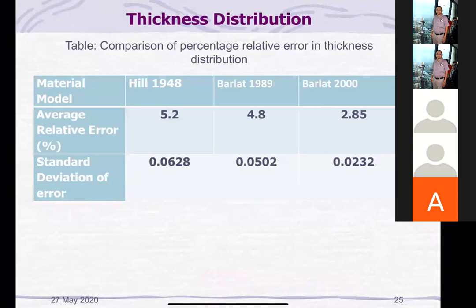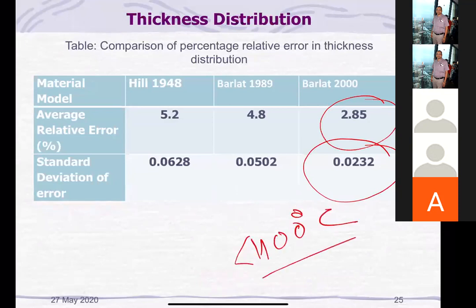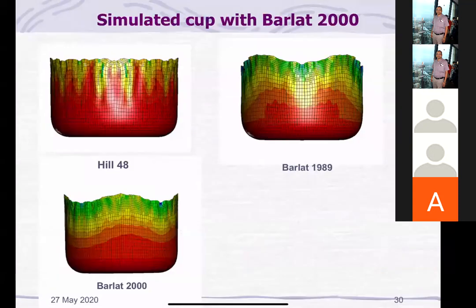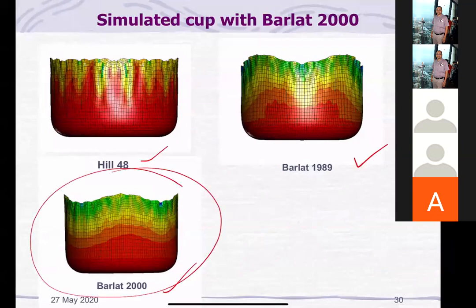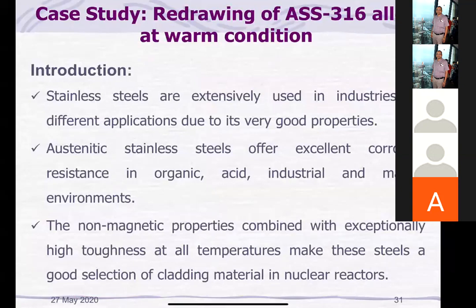So there's a comparison between Hill, Barlat 89 and Barlat 2000. The average relative error is 2.85 and standard deviation is 0.02, very, very small. So for titanium grade 5, below 400 degrees centigrade, we can use the Barlat 2000 model for prediction. These are some of the simulated curves for Hill 48, Barlat 89 and Barlat 2000. So this fits best. I will not be covering the case study on 316.